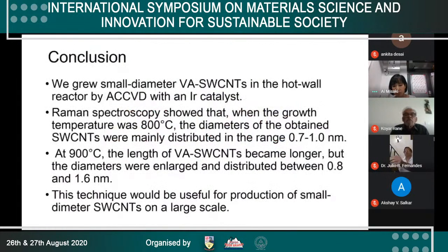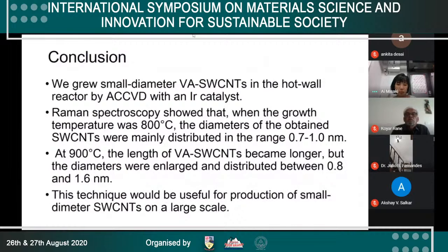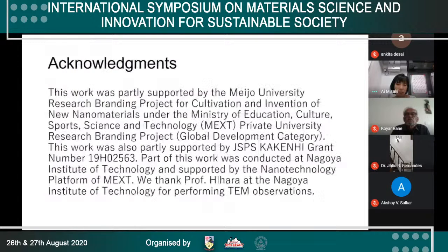Conclusions: we grew small diameter vertically aligned single-walled carbon nanotubes in the hot wall reactor by ACCVD with an iridium catalyst. Acknowledgement. Thank you.